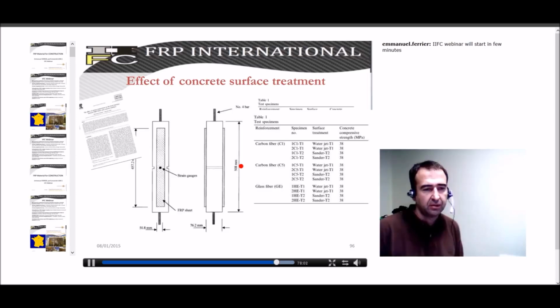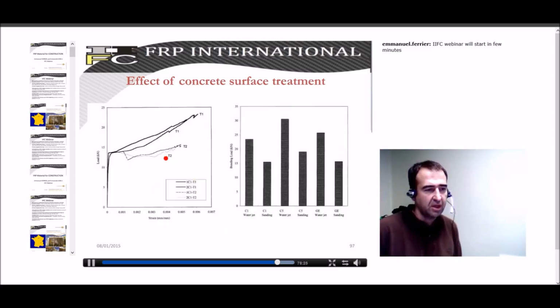This author has studied the effect of the surface treatment. All the surface treatments recommended are water jets, centrifugal. There is also a mechanical surface treatment, and this author compares different surface treatments to identify their effect. And as you observe, it seems that sanding is not the most efficient way to prepare the surface.